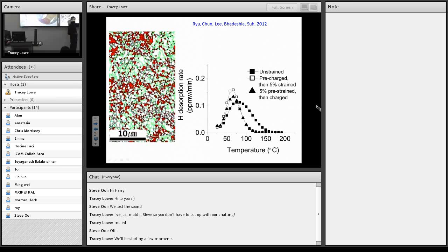This is the specimen which has not been strained. And these are specimens which have been strained so that the austenite in this particular steel has decomposed into martensite. And you can see that suddenly the hydrogen becomes diffusible. The hydrogen that was trapped in austenite will become diffusible. So that's a very interesting fact: yes, you want the hydrogen to end up in the austenite because it's a strong trap. But then if you do something to trip the austenite, you're basically providing an internal source of hydrogen to the ferrite. Not a good thing.